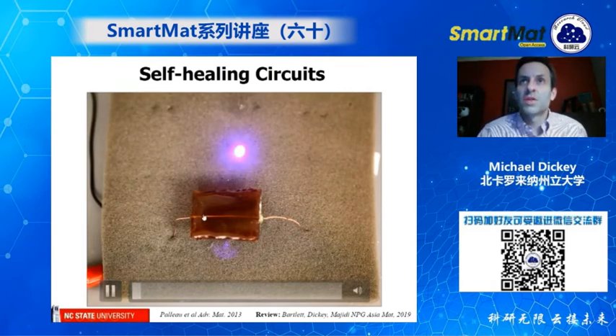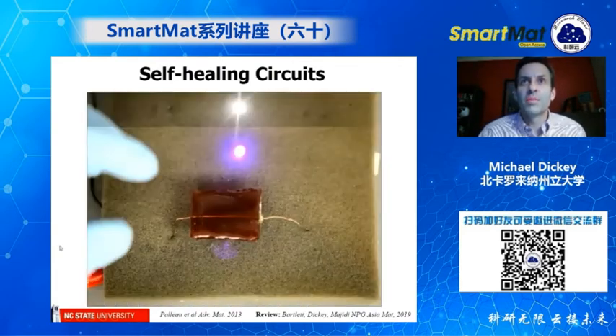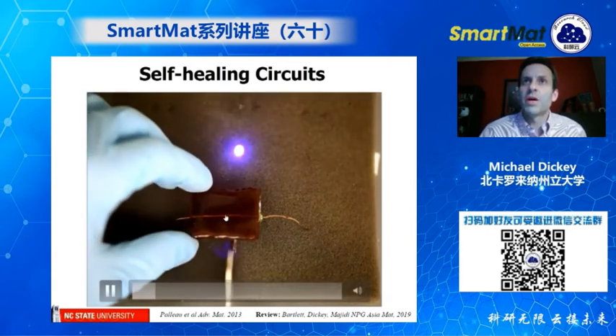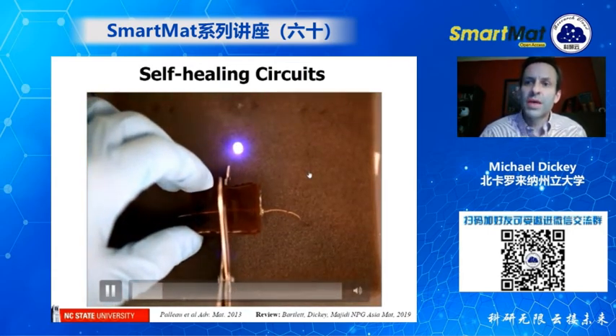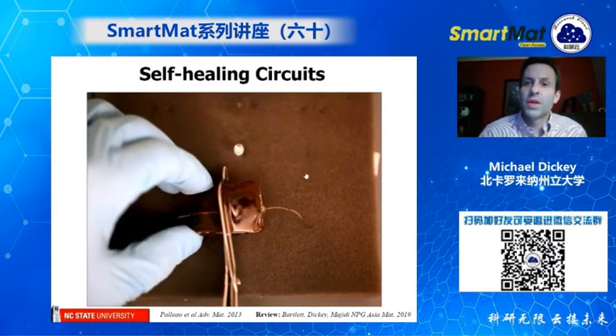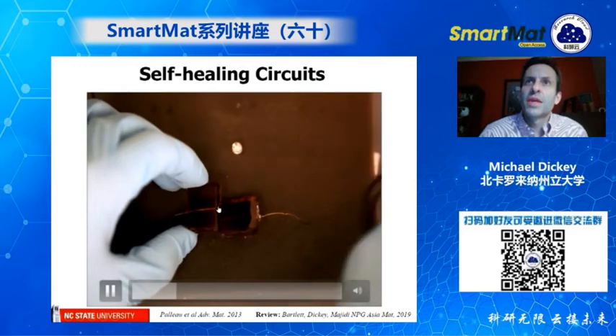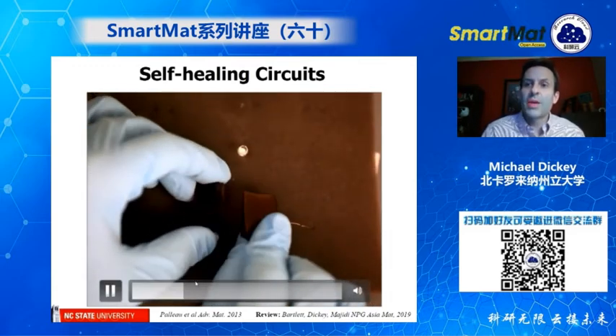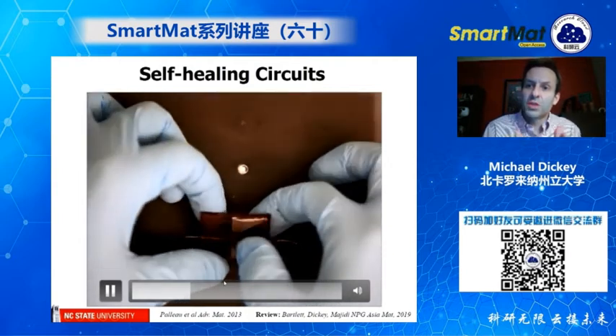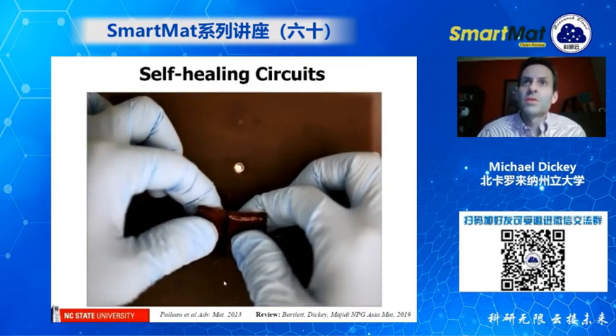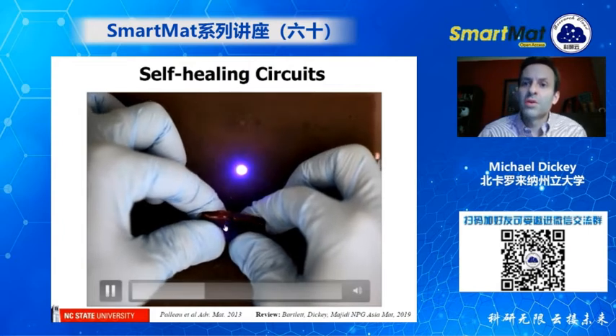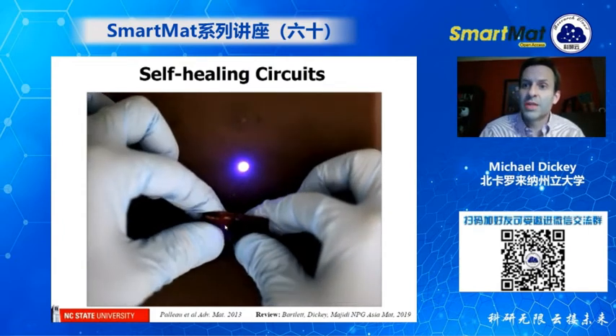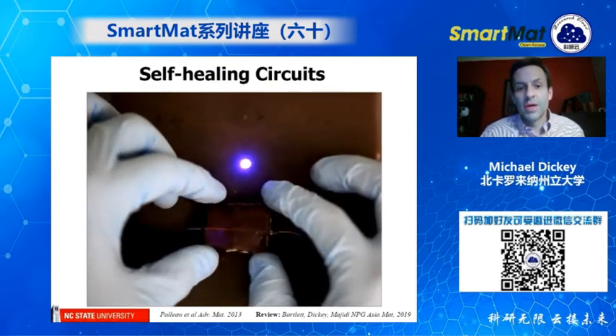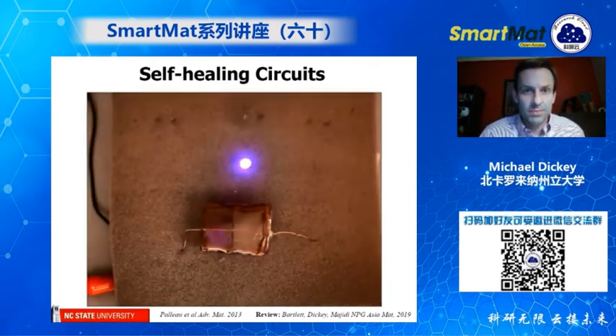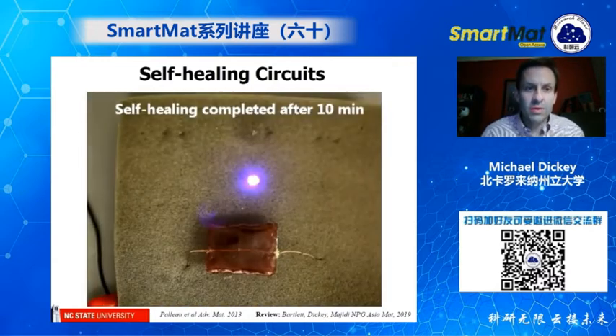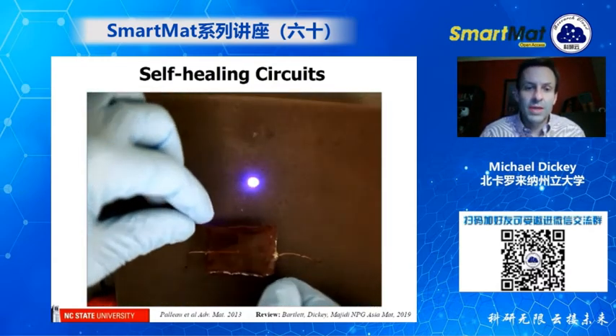For example, you can put the liquid metal, as shown here, in a special polymer. This is a self-healing polymer, and there's electricity going through this polymer that's lighting up this LED. Now, you can cut this with a pair of scissors, and it will break the circuit, and you can see that the light turns off. And the key thing is that the liquid does not leak, does not come out. In fact, it oxidizes so fast that it stays flush with that interface. So when you bring it back together, the circuit will heal electrically, and the polymer will also go back together because the polymer is held together by hydrogen bonding. And so if you wait about 10 minutes, the polymer will go back together and it will heal electrically. You don't have to do anything, you just wait, and the polymer will completely self-heal. And so it's regained its original mechanical properties.